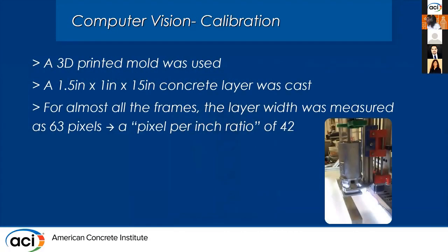And in terms of calibration, I first want to have a reference layer with accurate dimensions. So instead of printing the layer, I printed a mold, and I used a self-leveling concrete to cast a nice layer with exact dimensions of 1.5 inch width and 1 inch height, and then used my vision system to measure the width of that layer. It was consistently measured at 63 pixels, which gave me a pixel per inch ratio of 42. And you can see the picture on the right side.